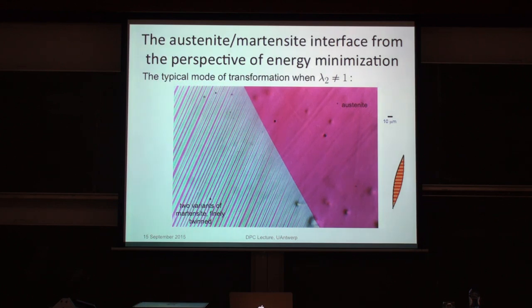So that suggests a third possible explanation for hysteresis, which is the following. So you start with a material with all austenite, okay, so it's completely the cubic phase, and you start cooling it. Now, we know that there are little bits of martensite, and they might look like this in an idealized form, that are waiting to grow and to form these interfaces. But as I just mentioned,